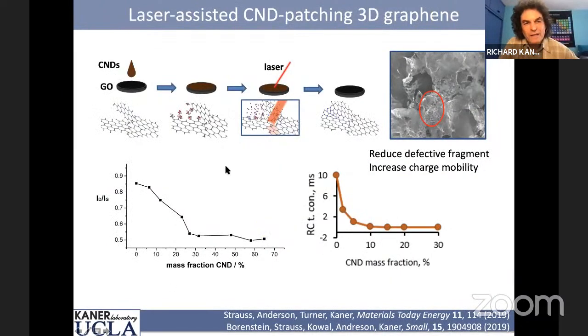And what we've done is we've looked at what happens if you put carbon nanodots into our synthesis from graphene oxide using a laser. And so we just simply add some carbon nanodots dispersed in water into graphite oxide. We hit it with a laser. And what's interesting is when we look under a microscope, we can actually find, here's the graphene, and here's where the carbon nanodots actually go in. And they seem to repair some of the defects in the graphene.